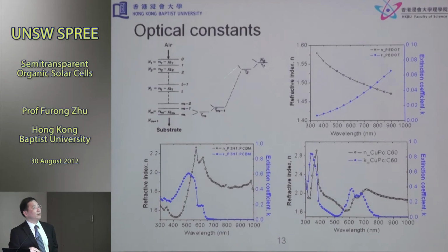Okay, so one way of doing the optical approach, one way we found very convenient, is the so-called optical admittance analysis. Essentially, when you deposit the first layer, you have two interfaces, and when you deposit the second layer on the first layer, the second layer can see the first layer and the substrate as equivalent to one surface. This is called admittance analysis. Theoretically this works for a system with any number of layers, so long as you know the optical properties of those materials, then you can simulate and understand how the light propagates, and where it generates the highest optical field. Therefore, you want to adjust the light propagation in the system such that most of the light is located in the blend layer, for example, the photoactive layer, where you want it to be absorbed more efficiently.